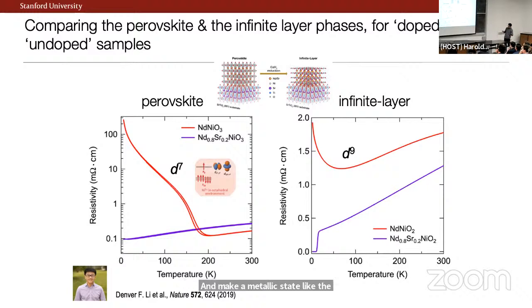So now we do this interesting chemistry. We pull out these planes of oxygen, and so we go from O3 to O2. And what we find is that for the doped phase, we indeed undergo a superconducting transition. So this multi-decadal kind of suspicion or hope that nickel oxides might host similar kinds of superconductors starts to bear fruit.